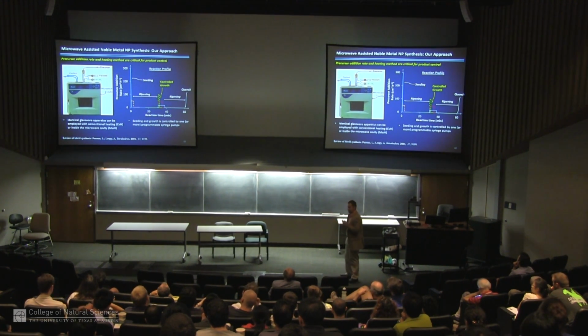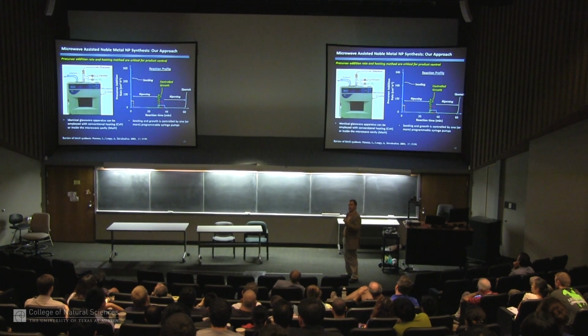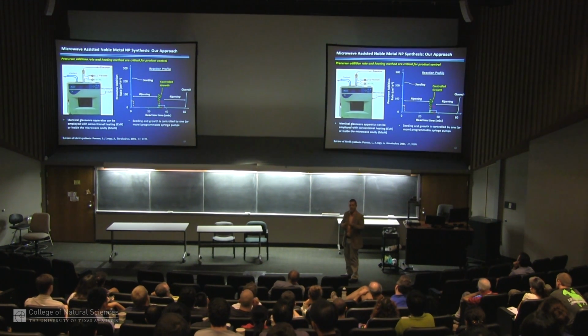Now the one thing I'm hoping to convince you of is that the difference between microwave heating and conventional heating is large, and it's all because the heating is a completely different mechanism. So if we take a polar solvent and we have to use polar reagents, they strongly couple to microwaves. The heating's more inside out, which is why you put a pie in the microwave and you heat it up, you can burn the inside of your mouth because the outside's cold and the inside is really hot.